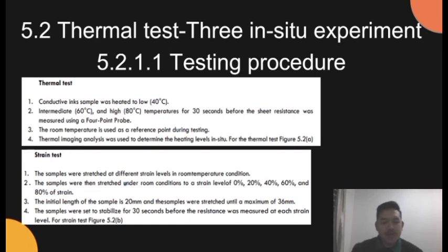The testing procedure for the thermal test: the conductive ink sample was heated to low temperature, which is 40 degrees, intermediate 60 degrees, and high 80 degrees for 30 seconds before the sheet resistance was measured using the 4-point probe. Next, room temperature is used as a reference point during testing. Thermal imaging analysis was used to determine the heating level in situ. The thermal figure will be shown later. Now let's move to the strain test.